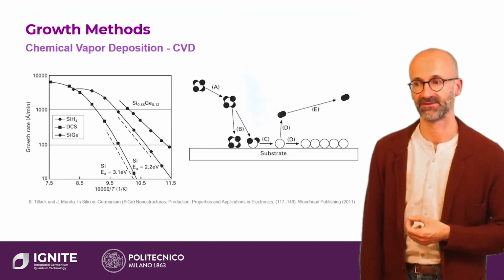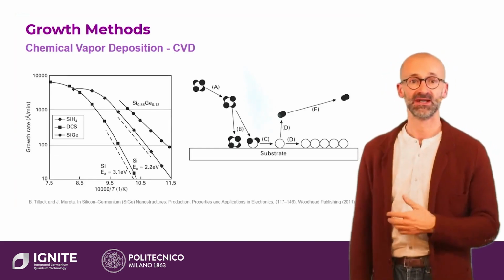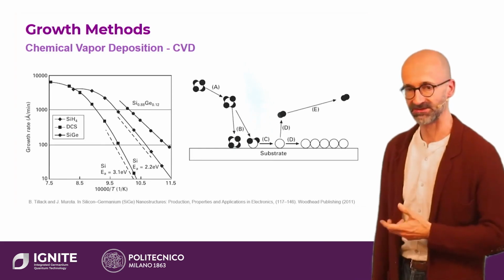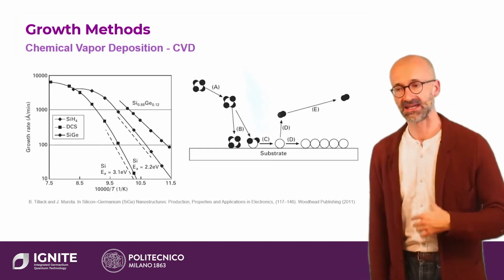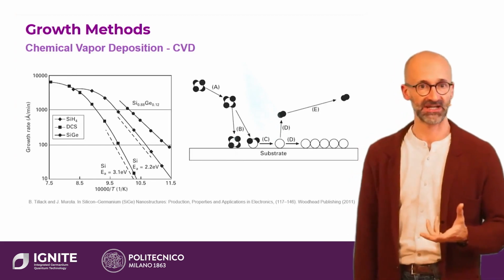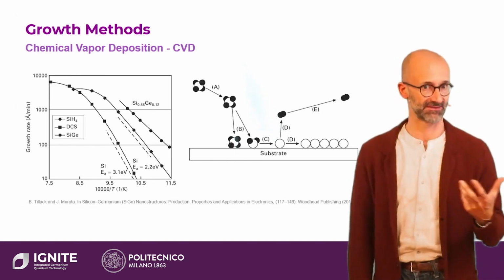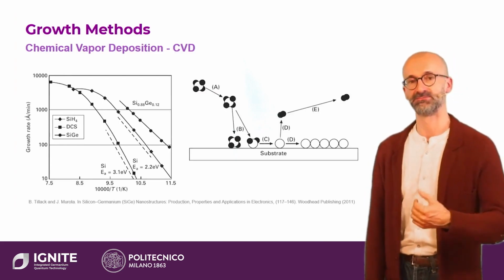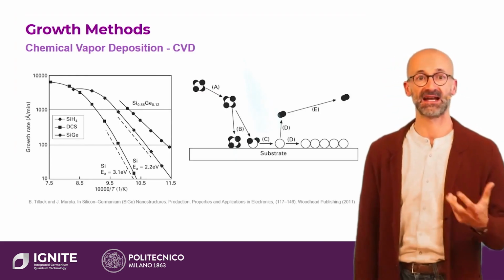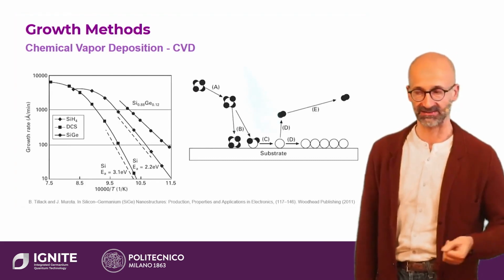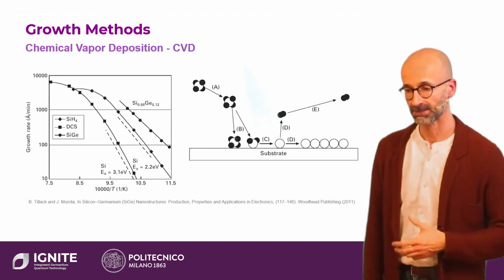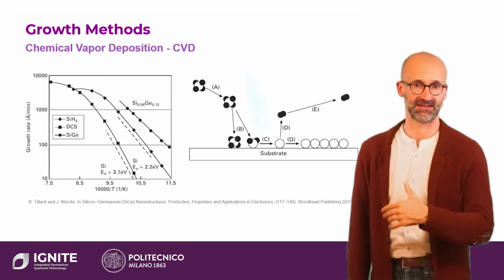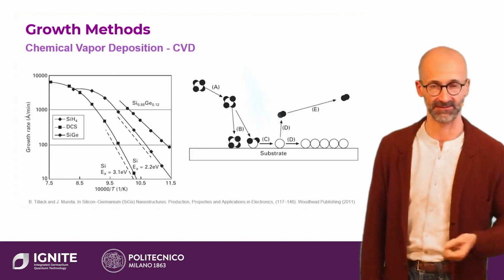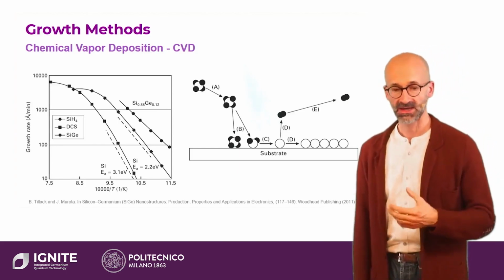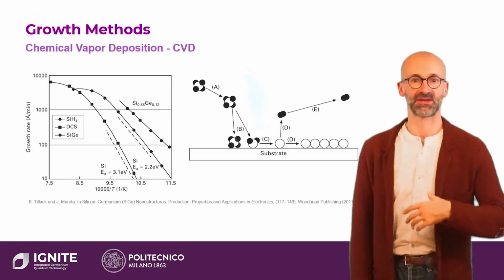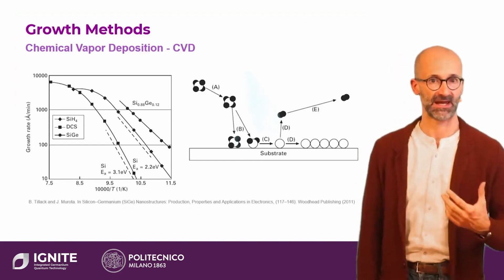The system used most often for industry now is reduced pressure, and this is a few hundred torr, something like that, in terms of pressure. In this case, gaseous precursors arrive in the growth chamber. Here the vacuum is not so critical because there is a background of gas, usually hydrogen, to bring these precursors through the system. These precursors are silane and germane, or various chlorosilanes in some cases, or even disilane. These are analogues of methane, but using silicon and germanium. They pass through the system, and the hot wafer is the reaction substrate for chemical reactions.